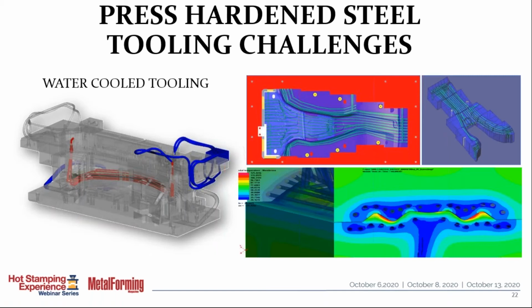The big challenges in press hardened steel tools are the water cooled tooling. So we have these cooling channels that we put into the tools, and they're not easy to put in. We cross-hole drill them, and we try to keep the holes as small as possible and put as many holes or channels in as possible. That's for optimum efficiency of transferring the heat from the surface through the tool to the water channel and then into the water and out of the tool. But this adds a lot of complication to the design, as you can see.